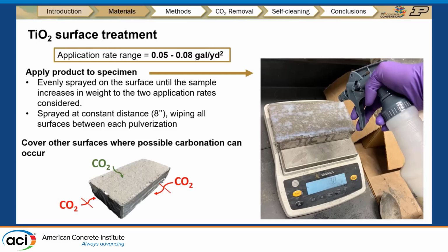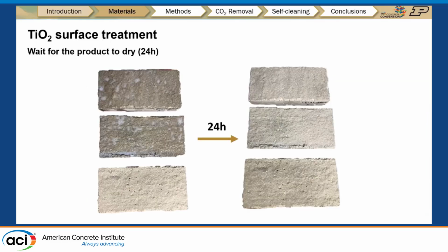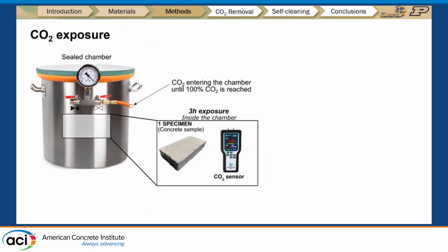After that, we cover the other surface where possible carbonation can occur and wait for it to dry for 24 hours. So our method for the carbon dioxide capture is that we have a sealed chamber. Then we put our titanium dioxide treated and untreated samples with a carbon dioxide sensor into that sealed chamber. Then we turn on the valves and let carbon dioxide enter the chamber until 100% carbon dioxide concentration is read by the